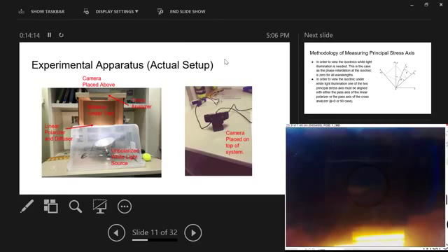So the reason why we used the incandescent bulb is because the spectrum of it is more continuous than that. And we saw that in some of our measurements, and it messed up some of our measurements. So essentially, we took this incandescent bulb, and then there was a diffuser, which was a sheet of paper directly underneath it, and then a linear polarizer, and then the sample would be placed there, and then the camera was set on top right here.